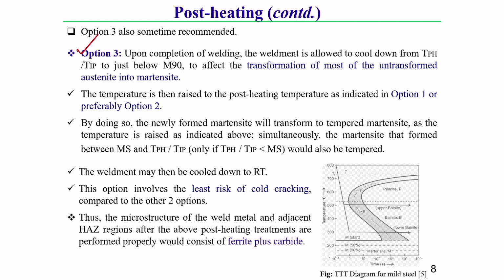Graphically, I am showing it here. Let us consider this is our preheat temperature TPH, and this is our room temperature TR. We start the welding from preheating temperature, then we heat the specimen, then it is cooled down to preheat temperature. Instead of holding the cooling at preheat temperature, here we cool further. This is the martensitic 90% transformation line, M90, and below this M90 we reduce the temperature.